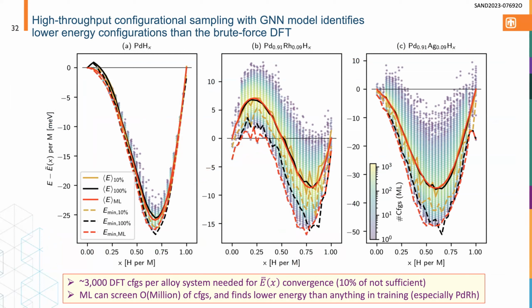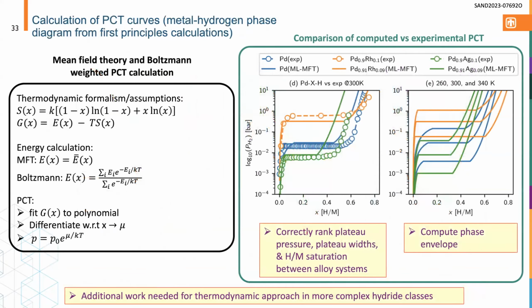So you can see if you use DFT, that's essentially the orange and black lines, you get a lot of noise in your signal, which adversely affects your ability to predict the PCT curve. But in red, if you are able to screen tens of thousands of configurations, you can completely converge these distributions. And that's what's ultimately going to allow us to predict the PCT curves. So in reality, we screen millions of configurations for this. So that gives us the ability to compute the PCT curves.